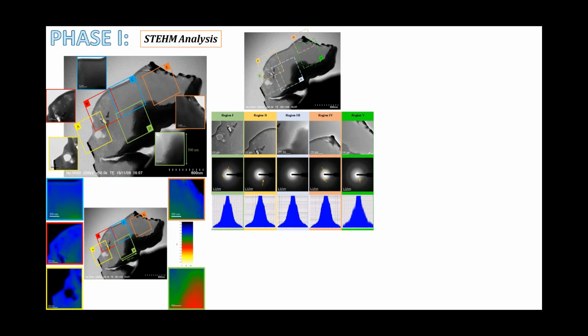Thank you, Pejman. I have a question from a student who asks if you have an idea from which temperature the crystallite will create a self-healing process, or in other words, if this crystallite behavior is attached directly to the temperature of the environment. So generally speaking, the concrete itself, in terms of the hydration products, and I'm expecting something similar for the crystalline mixture: when they are exposed to higher temperature, they react faster, and you will be able to cure these crystals faster. So imagine if the temperature is increasing, let's say by 5 to 10 degrees, I would expect to have the growth of crystals faster and also see more hydration happening inside.